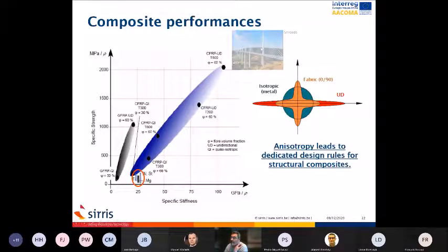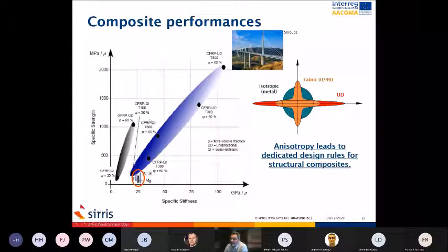But in fact, you have a UD material. So if you want to realize a shroud, for example, for a bridge, no problem, that's the perfect product. But now, if you want to use it for a more common and more universal performance product, you have to take into account the different parameters. T800, if you come to a more conventional fiber, which is the T300, you'll see that you have a decrease of the performance. If you are now talking about quasi-isotropy in terms of UD direction, this point comes here with all the other parameters remaining the same. So that means that you are now closer to the metal, but still with an interesting improvement.